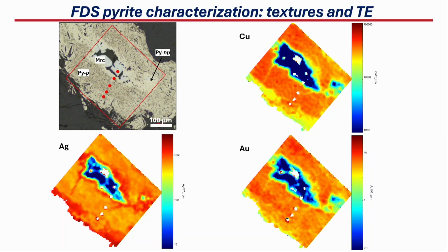which displays porosity, and also some higher values on the edges. And finally, gold. Well, gold we can get up to 10 ppm in pyrite, and again, mainly in this porous pyrite type as we see in the vein.